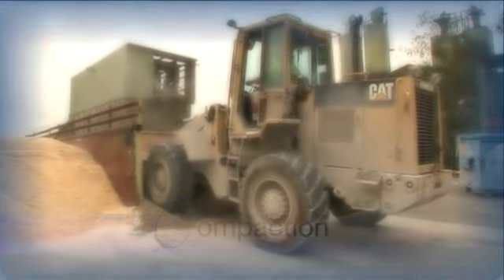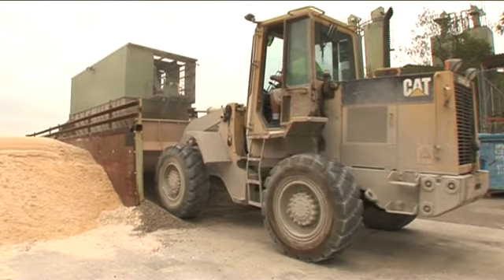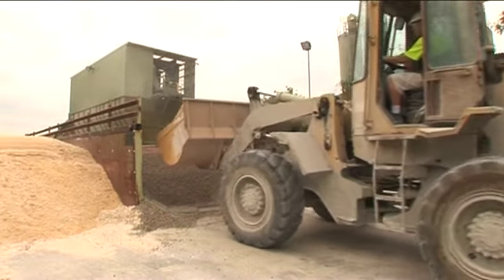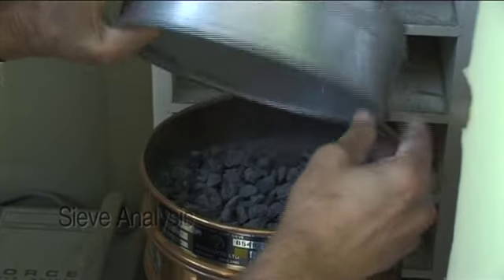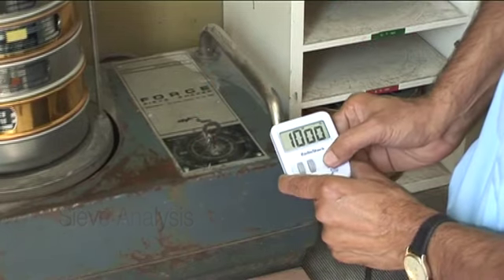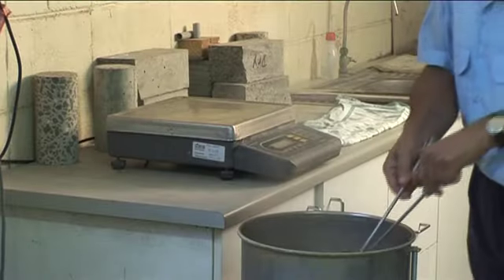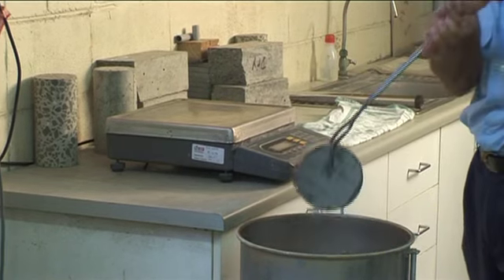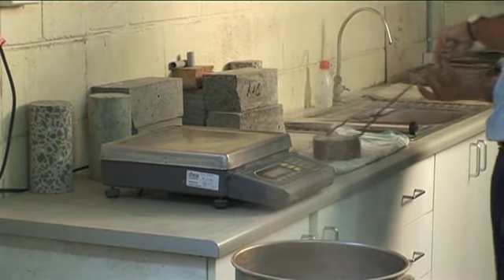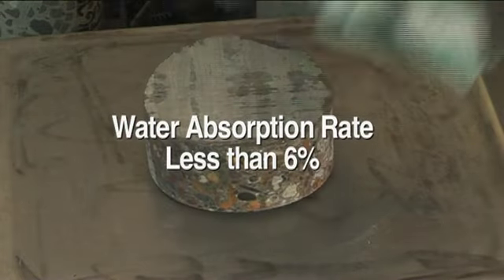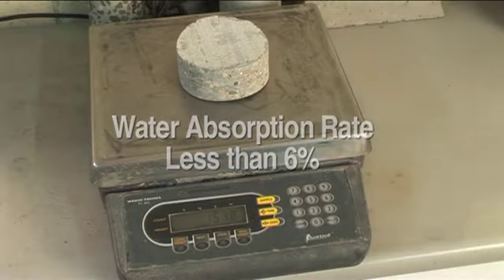Mix design and manufacturing processes ensure that the carefully blended high-quality raw materials used in concrete pipes will compact to form a high-density concrete with a minimum of voids. The factory-based manufacturing processes ensure that the concrete is adequately vibrated and ensures a maximum of compaction without segregation of the components. To determine the effectiveness of this, the water absorption test, defined and conducted in accordance with AS/NZS 4058, indicates durability performance and must show results lower than 6%.